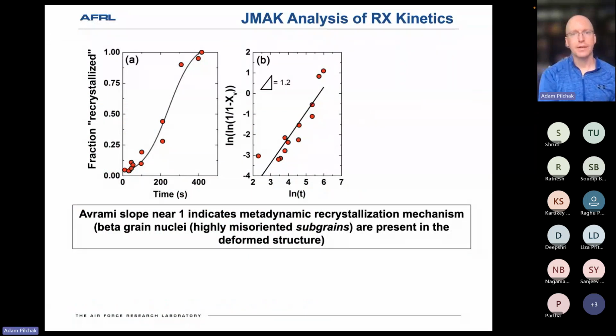So we use JMAK kinetics to analyze the recrystallization mechanism. Here we're plotting fraction recrystallized over time, and then the JMAK analysis, double log of 1 over 1 minus the fraction recrystallized versus the log of time. You fit a slope to that data, and the slope tells you something about the recrystallization mechanism. In this case, the slope was about 1.2. And in comparison to other material systems that have been widely studied, a JMAK slope of around 1 is consistent with what's known as metadynamic recrystallization. And metadynamic is just a fancy way of saying that the recrystallization nuclei are already present in the deformed structure.